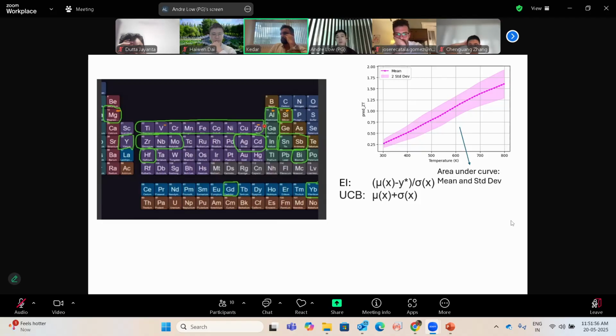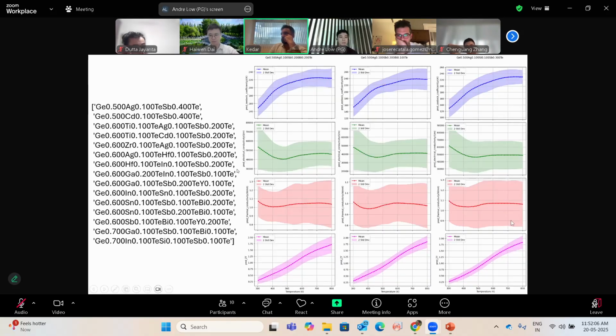So the idea is that we first started by looking at the aggregate ZT, the area under the curve of the ZT. So we wanted to optimize for compounds with the highest area under the curve. These are just some of the top 20 compounds that were flagged, with the predictions for their properties and ZT. This is what we have at this stage. This is my last proper slide. But there's nothing beating state of the art here. Yeah, unfortunately. But can you do an exploration with the BO? This is not BO, this is just a forward model, right? This is essentially a one-shot optimization.